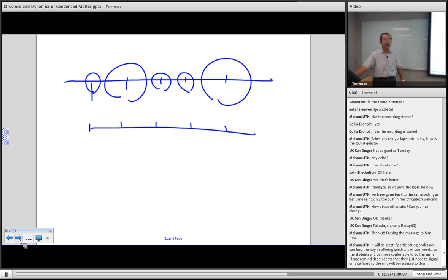So this kind of size difference produces apparent displacement. Because this one compared to the average is moved a little bit, and this one also moved a little bit, and this one is moved a little bit to the left, etc. Right? So this kind of randomness produces an apparent phonon. This is not a phonon. It's an atomic displacement due to this randomness. And this happens all the time in the sample.